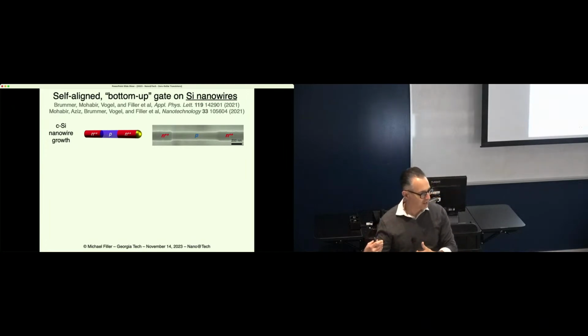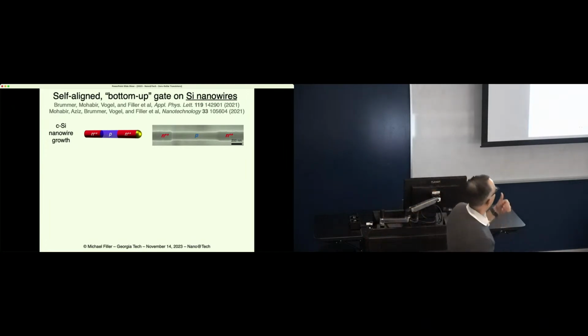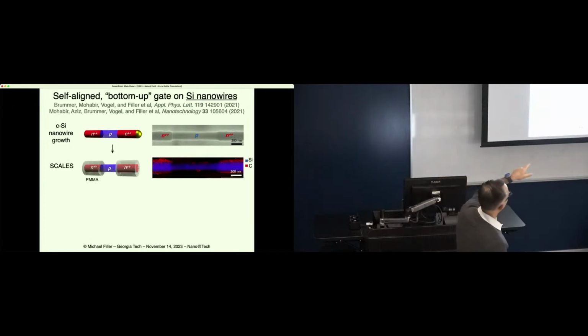The real challenge is making this work on nanowires. And so there I'm showing a nanowire with a slight selective etching just to show where the P region is. Here is EDS in a TEM of a wire that has been selectively etched with the PMMA. And so what you can see is the red regions, the carbon from the PMMA, are still on the source and the drain, and a lot less is on the channel region. So we've been able to etch it off selectively. It's not perfect, but it's not horrible either.